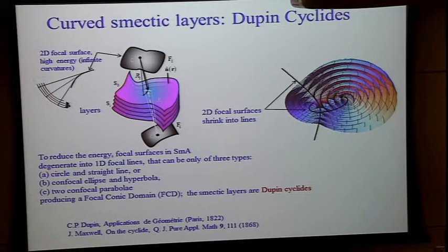aware of this geometrical solution because he wrote an article about the cyclide and said if I have the source of light somewhere that is a piece of line here and the image is a piece of line there, then the waves propagate by the Dupin cyclides shape. And this is true because this construction has an interesting property that all the director lines in this configuration are straight lines. It's like the wave vectors of the beams propagating in the isotropic medium. And the director lines join the points on the hyperbola to all the points on the ellipse and vice versa.